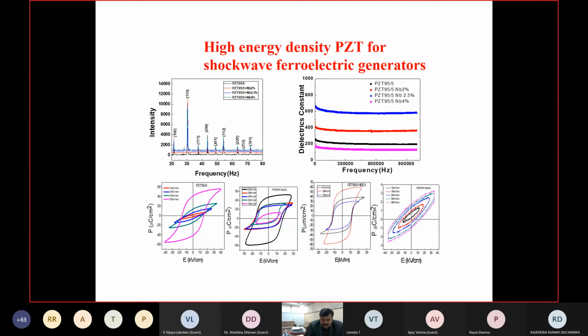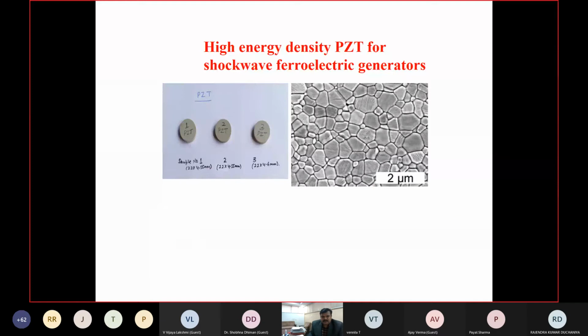Here you can see the lower plots. Those are between polarization and electric field. So electric field units are kilovolt per centimeter and polarization are microcoulomb per centimeter square, right? So with increase in the applied field, you will see the saturated loops, their area is also increasing. So these are the particular pellets we have made in our lab, and this is the SEM micrographs of the top surface, which is showing the grains.